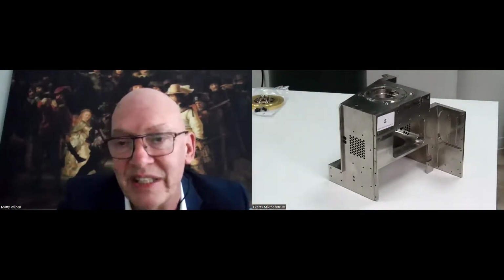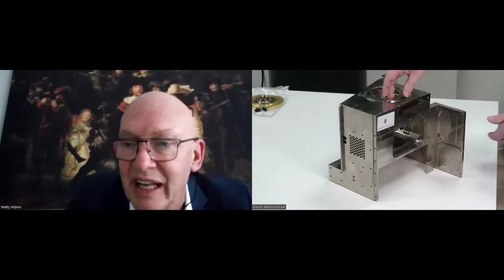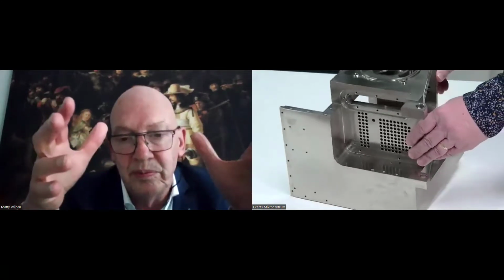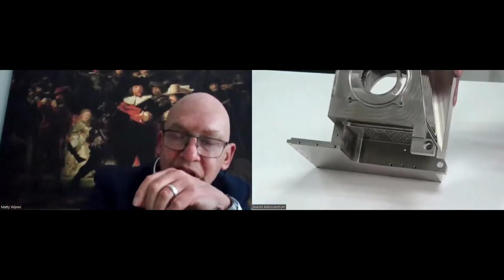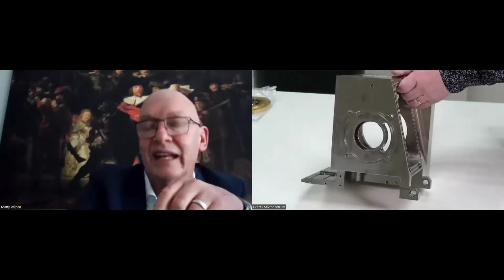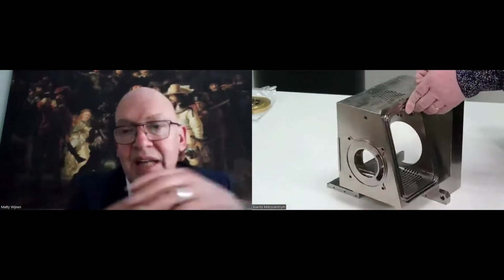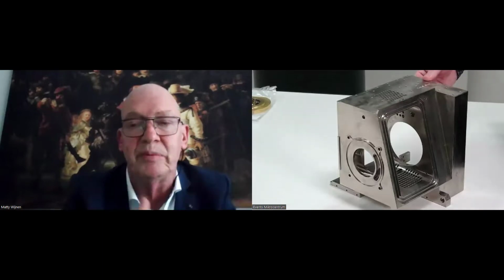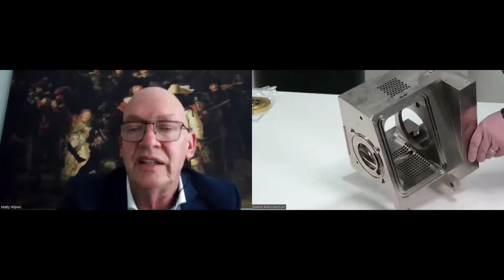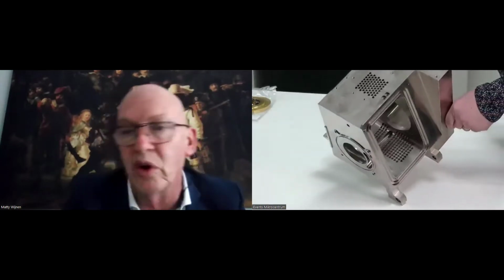That's a big one, and that's a typical chemical nickel plated part, which has all these problems inside. What you see here is you have a lot of holes in this part, and all these holes, of course, contain oil after treatment. Now, what we do is normally we clean those holes out, but when you start processing them, there's always a direction, and that's something: how do you put your part into the bath? You always have to make sure that no solution stays in the holes, and that the oil which is in the hole is coming out. So producing these parts is very difficult, and it means you have to make a rack or a fixture so that your part can turn around in the bath to make sure the holes are emptied. Nickel is coming in, but is also going out, and that kind of stuff.